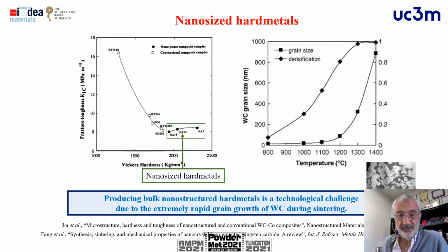Another field that we want to explore is to work with particles of very small size in order to obtain the so-called nanosize hard metals, as you can see here. In this graph, we can see how the fracture toughness usually is reduced as much as we increase the hardness of the cemented carbide, but only if we use nanosize hard metals can we maintain some level of fracture toughness, even increasing the level of the hardness.